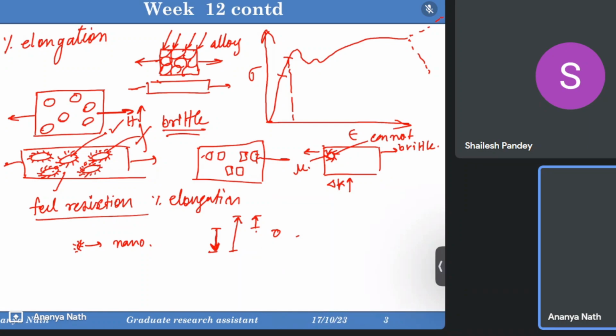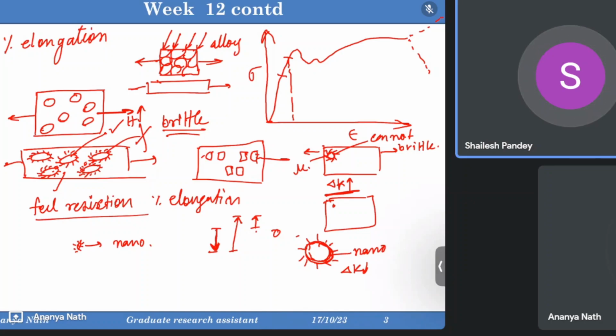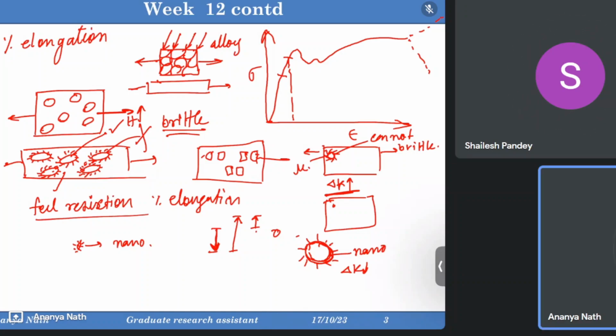But if you are mixing particles in nano dimension, then what will be the case? If this is the nanoparticle, the area having the interface is lesser in this case. So the stress intensity factor arising in this area will be less. Del K is lesser than in this case, so it can get elongated. But ma'am, the interface is more in case of a small size particle. Yes, but that depends upon how many particles you are adding.